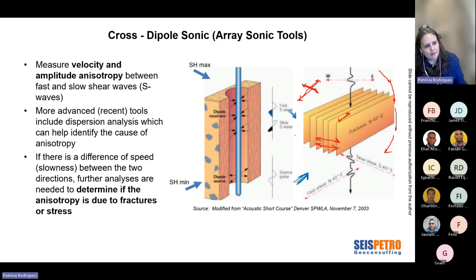When you have a big stress anisotropy between these two, your pores also align with the stress and your grains. Everything deforms in a way that even if you don't have fractures, you're going to see a difference in shear velocity between the two directions. If the difference between these two is large enough, even if you have some fractures, what you're really measuring is the difference in stress.